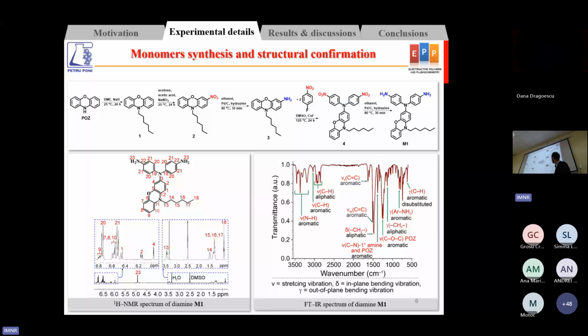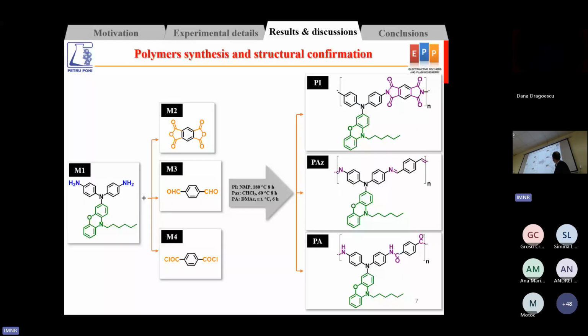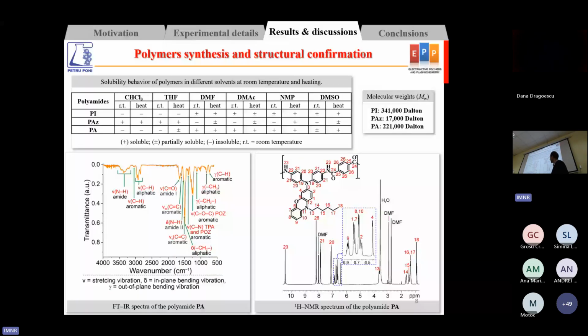Based on this diamine, 3 categories of polymers were synthesized: polyamide, polyimide, and polyazomethine, by polycondensation reaction following different reaction conditions. The structure of the polymers was also confirmed by NMR and IR spectroscopy. In this example, the polyamide showed the corresponding signal of the amide group at around 10.5 ppm. We tested the solubility of the polymers. The polyamide and the polyimide were soluble in polar solvents, while the polyazomethine was also soluble in chloroform. Also, the polymers showed high molecular weight, typical for the class of polymers they belong to.